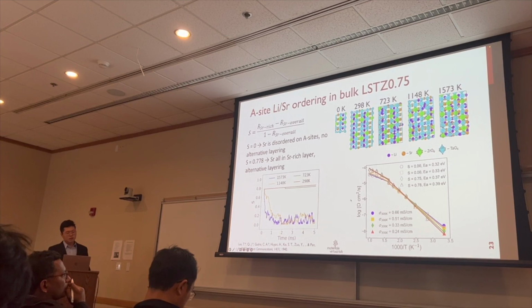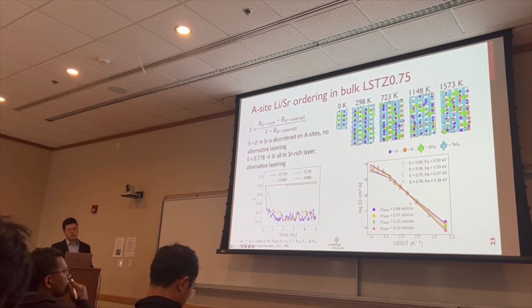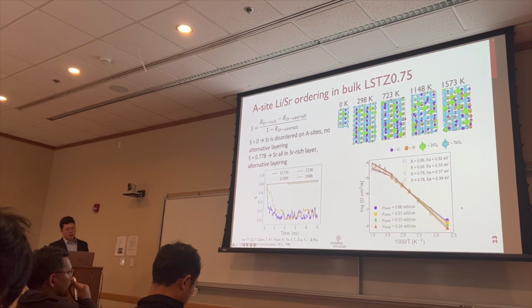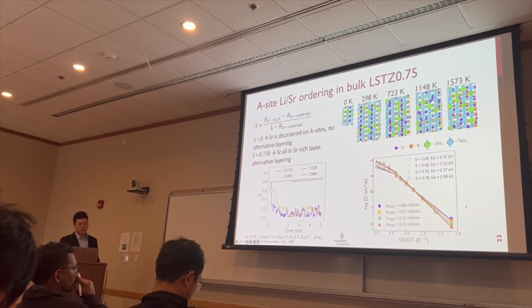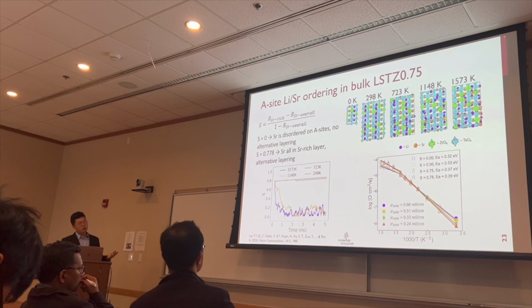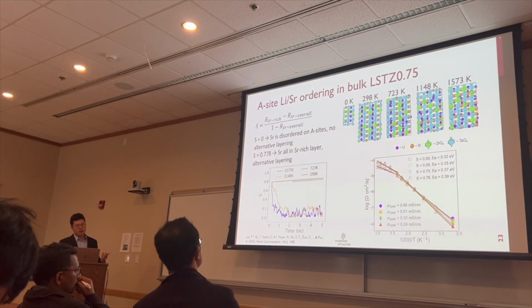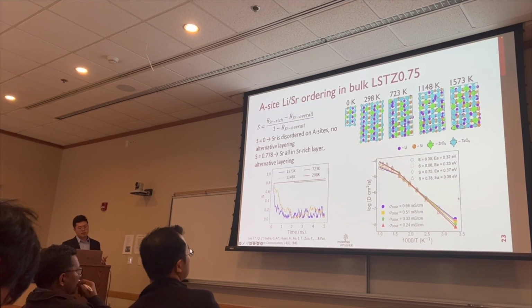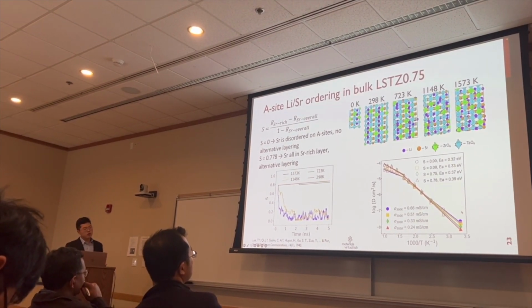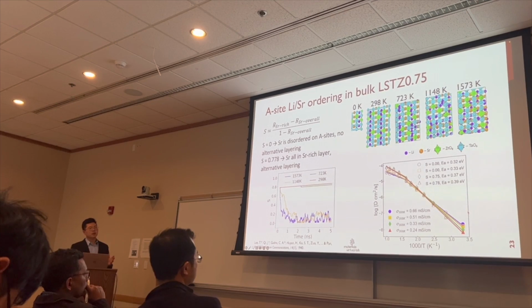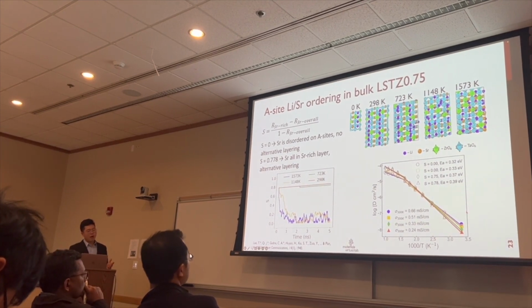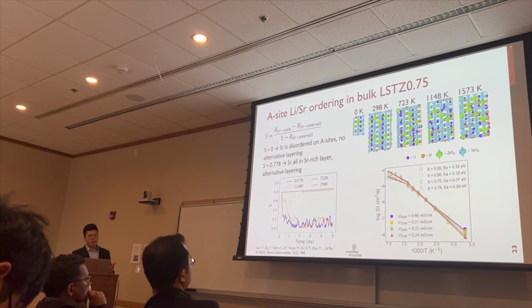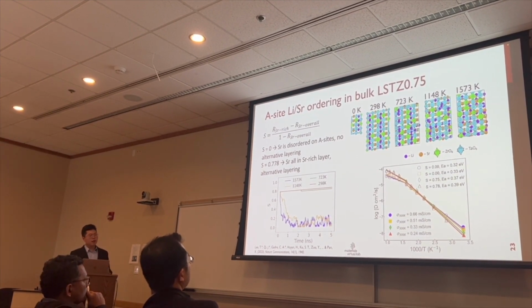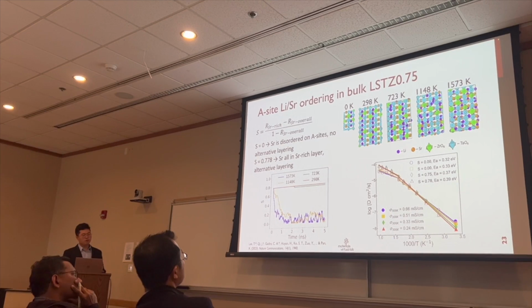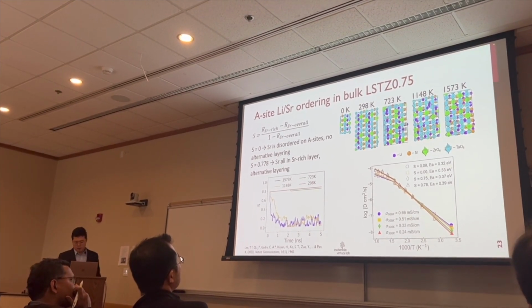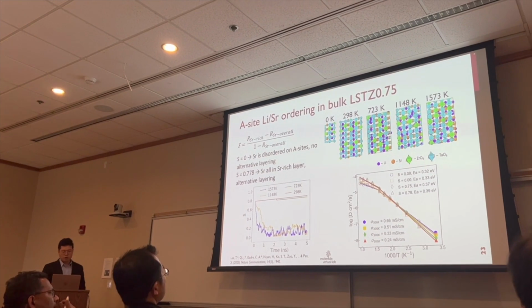And we also use molecular dynamics simulation to study the diffusion for different models obtained from MCMD simulation at different temperatures. And we see that the structure model that has the more disordered A site gives higher ionic conductivity. This trend has been reported for the lithium lanthanum titanium oxide case, where higher calcination temperature can promote A site disordering and thus increase the room temperature ionic conductivity of the bulk system by a few times. And this is a good verification for our model.